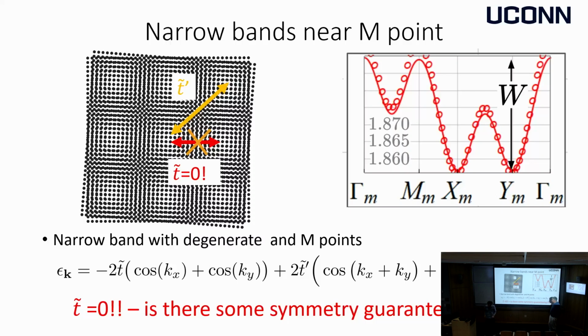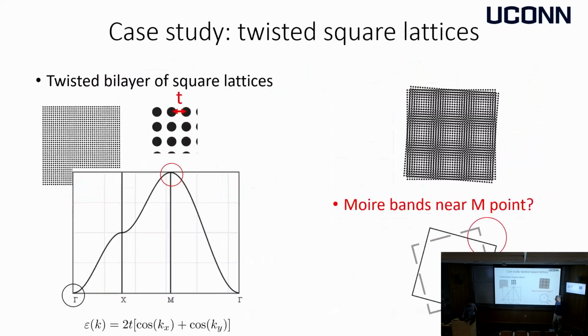Not quite. The degree of freedom that does the heavy lifting here is the momentum of the electron in the initial Brillouin zone. In some sense that's a wrong picture, but if I plot the wave function at this point, it's changing color every other site. And if you take two of these and twist, you will see that there's actually a big difference emerging between nearest neighbors. So the heavy lifting is done by these electrons actually having non-zero momentum within each layer.